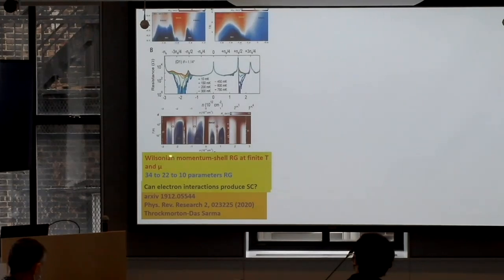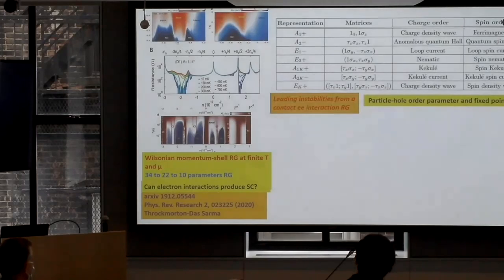This is a very formidable RG. I mean, we have a postdoc, Robert Throckmorton, who, I said the full RG is impossible. It's a 34 parameter RG. Basically, people do one or two parameter. With symmetry, you could reduce to 10, but this is really a 10 parameter momentum shell RG. And what he found is that almost every phase you could think of, there could be a phase transition. This is the problem with RG. It tells you what is possible, doesn't tell you what actually happens. It's a contact electron interaction, but we found lots and lots of fragile states, which I think is consistent with the experiment. No two samples show exactly the same phase diagram.